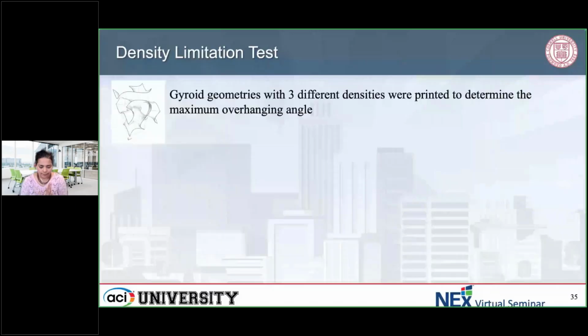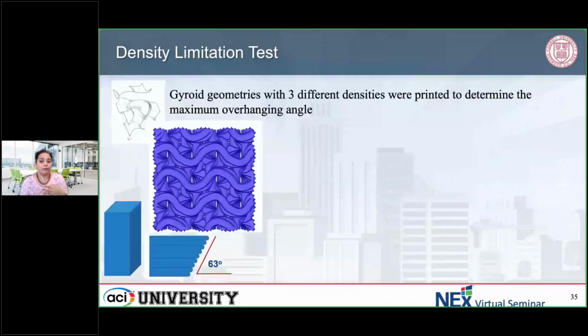So if you were to print a layer on top of each other, that would be like a 90-degree angle. But here, let's say we want to print layers that are at a 63-degree angle, or a 56-degree angle, or a 45-degree angle. So 45-degree would be the steepest cantilever, and it would use the least amount of material.